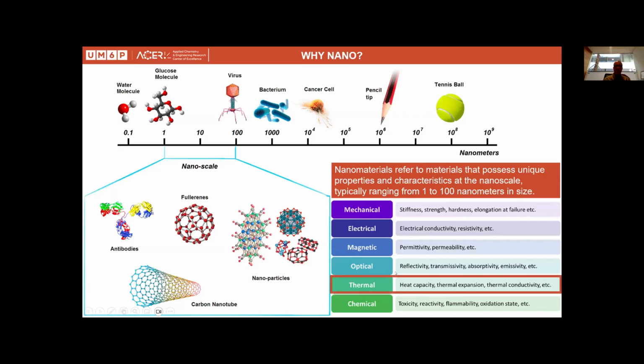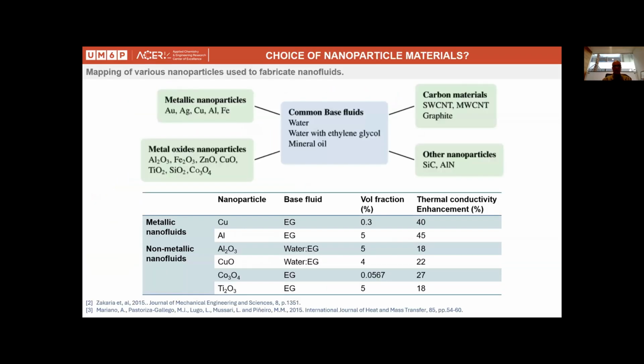Of course, in our case, we're trying to reduce the size of some kind of materials, metals, metal oxides, in order to enhance the thermophysical properties of these materials to be injected in conventional heat transfer fluid and to create nanofluids. So we are looking at increasing the heat capacity, reducing thermal expansion, or increasing the thermal conductivity of our nanofluid systems, which means this nanofluid can contribute to higher efficiency when it comes to CSP systems or solar thermal systems in general.